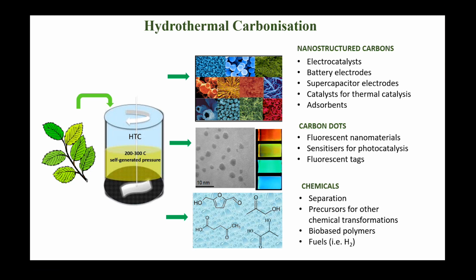So basically, through this process that I call the hydrothermal carbonization process, you get three things at the same time. You take biomass precursors that are rich in carbohydrates, and I'll come back to this, and you turn them into these black precipitates, which you can then nanostructure using materials chemistry tricks, and you get carbonaceous materials. So a lot of nanostructured carbons form here at the bottom.